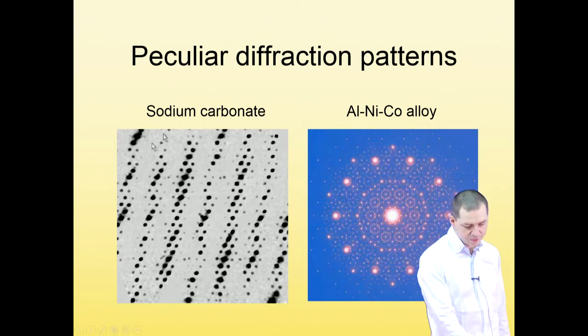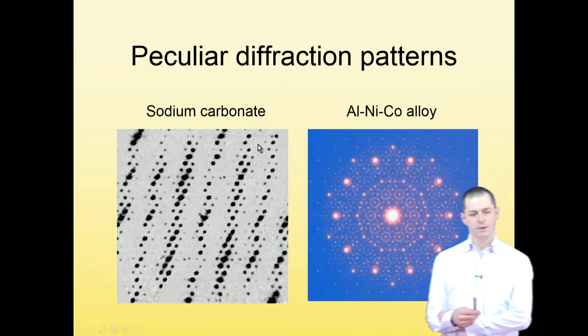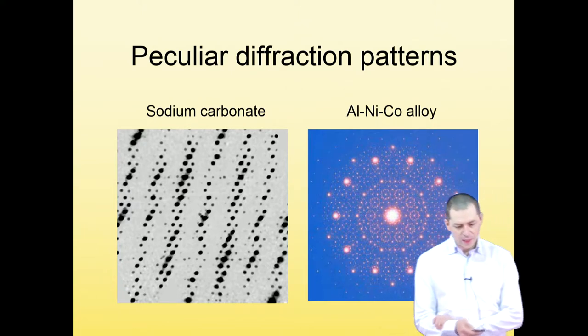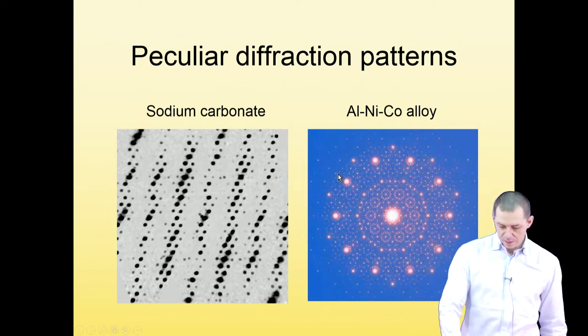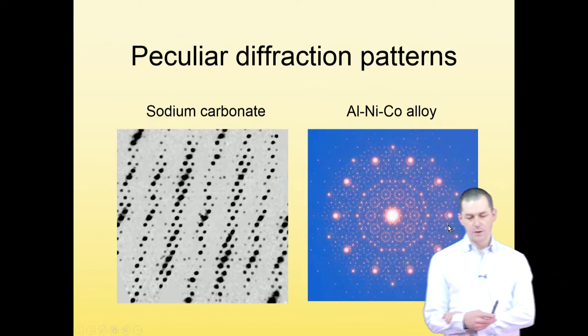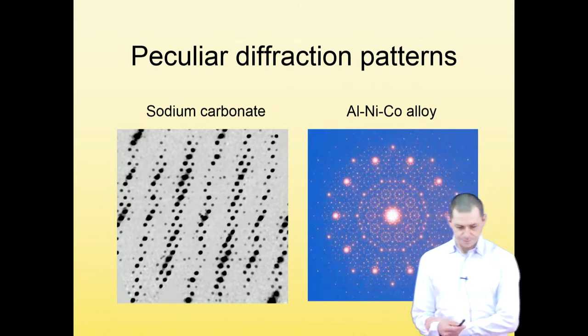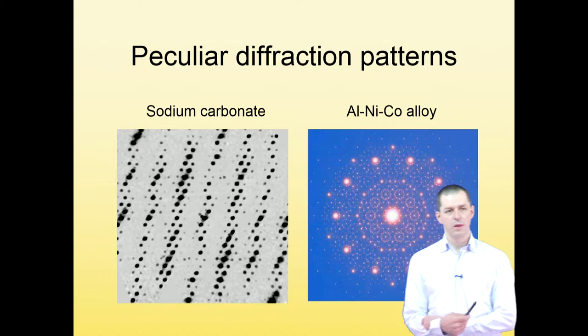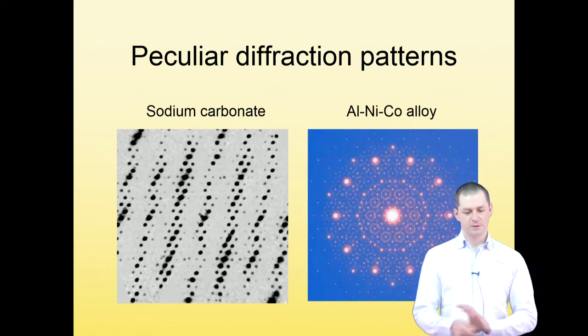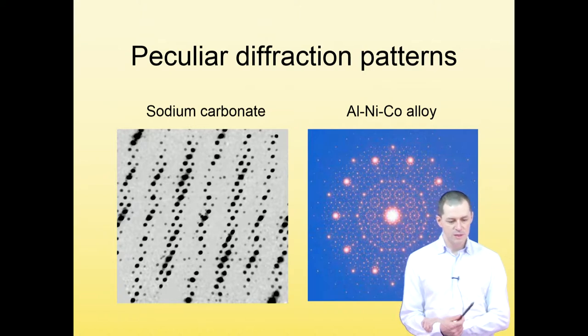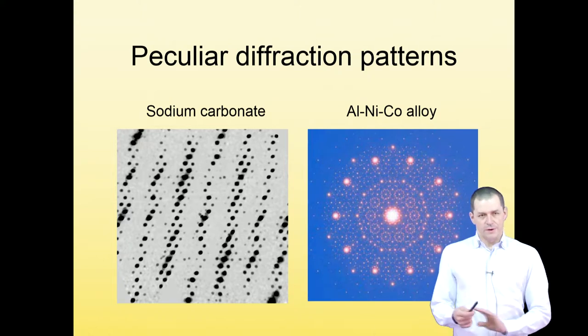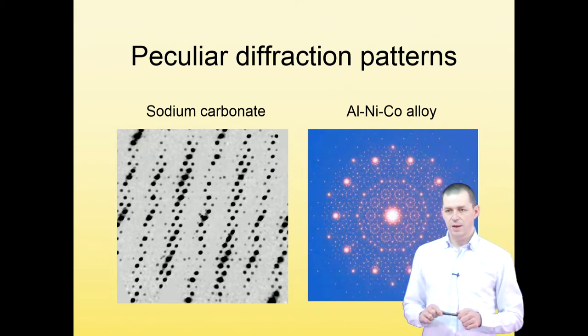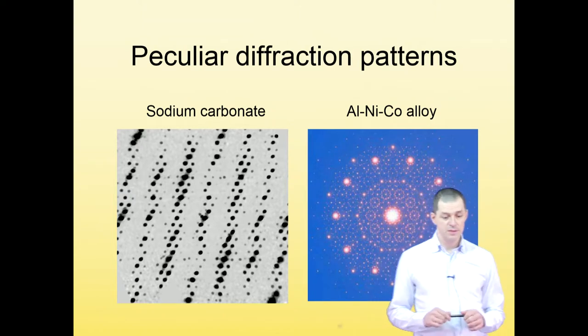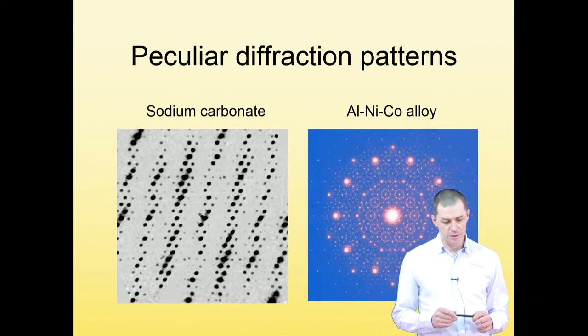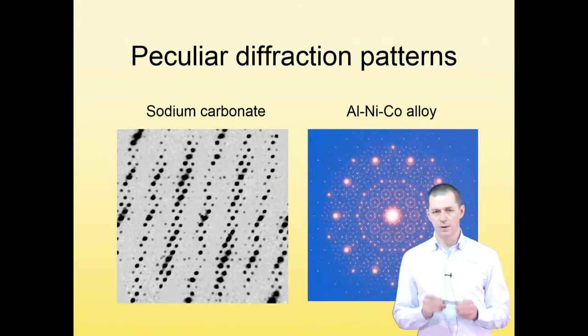On the left side, this is a section through the diffraction pattern of sodium carbonate. And on the right side, a diffraction pattern of an aluminum nickel cobalt quasicrystal. These are the representants of two quite fundamentally different types of non-periodic structures, the modulated structure and the quasicrystal. Both are non-periodic, both can be described in higher dimensional superspace, but the approaches to the description of these two classes of compounds are quite different.